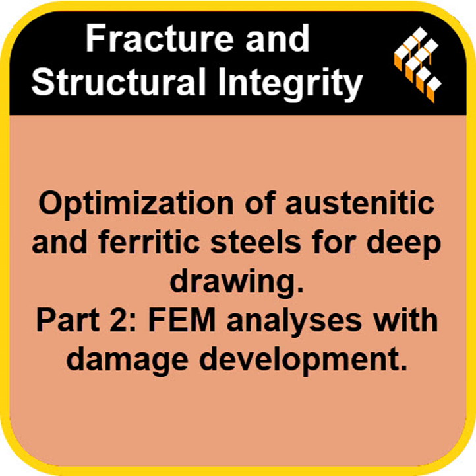Right. The actual stress keeps going up even as the neck forms, but the standard engineering stress-strain curve calculation fails. So the researchers had to figure out how to model that true stress behavior right up to the breaking point. How did they crack that? They used a really clever iterative approach. First, they did physical tensile tests, carefully measuring force and deformation using a camera tracking a grid on the sample, all the way to fracture.